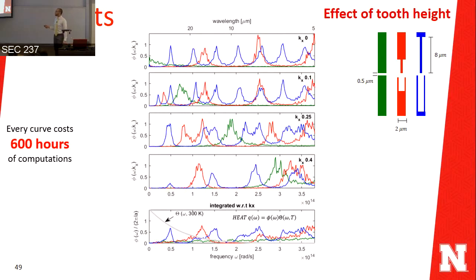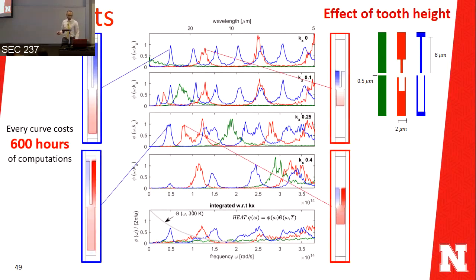The heat transfer calculation is done by just multiplying this curve, this theta, with the integrated transmission factor. So the most important frequencies are the lower frequencies here. And to give a sense of how it looks, these are the modes that are propagating at wave vector equals 0. They are standing waves here, and these are propagating waves in the x direction.